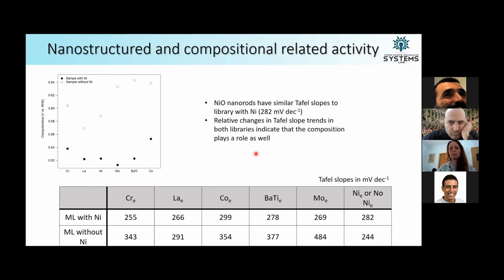But if you look at the sample that does not contain the nickel oxide, the nickel inside it, we already see quite large changes in the Tafel slope, meaning that the chemical compositions play a more important role over here as the active components towards oxygen evolution. And even more so, you can see that the trends are quite similar. So we first have a reduction and then an increase for both libraries. So the chemical environment does have an effect in the library containing the nickel as well, but not such a high effect as the nickel oxide nanoclustering within the nanostructures.